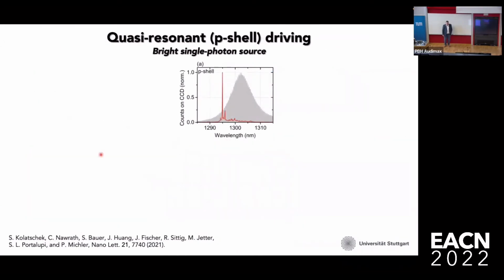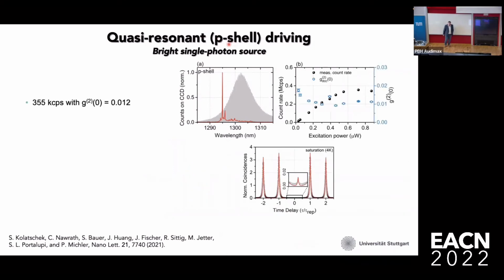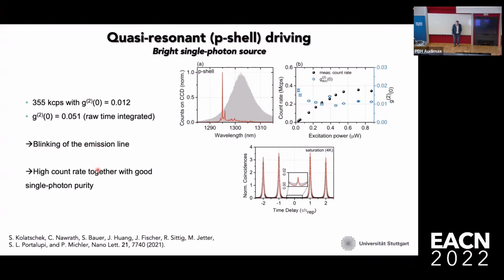Just to flash some examples quickly, there you see a single photon source emitting in the telecoms O band, in this case driving via the P shell, an excited orbital state. On the right-hand side you see the G2 of 0, and at the same time the count rates, which go up to around 500,000 or so. You also see that it is still blinking, but the count rate is very high and it produces a very nice single photon purity. If you're interested in these telecoms dots, please take a look at this recent publication from Peter's group last year.